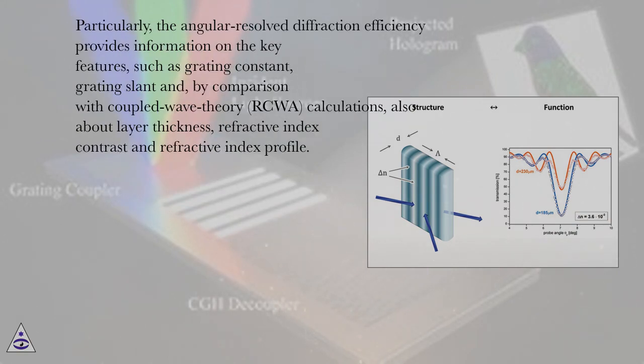Particularly, the Angular Resolved Diffraction Efficiency provides information on key features such as grating constant, grating slant, and by comparison with coupled wave theory RCWA calculations, also about layer thickness, refractive index contrast, and refractive index profile.